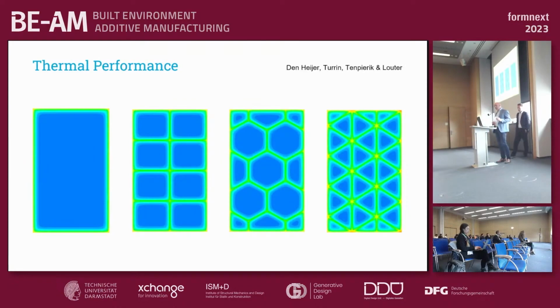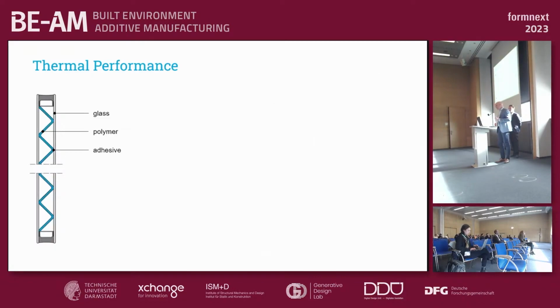Yeah, so far we have mostly looked at the structural performance of the panels, but thermal performance is also an issue, of course, that we need to have a closer look into. On these images, you can see some models of the thermal model, and you can see that we are losing heat at some points, and that's where you expect the core is touching the glass. So there we see some thermal bridging happening, because normally an IGU or insulating glass panel doesn't have this core inside. But now with the blue core that I drafted there, you see that there's a thermal bridge coming from the left to the right-hand side of the glass, bringing your heat or your cold to the other side of the panel, which we would like to prevent, of course.